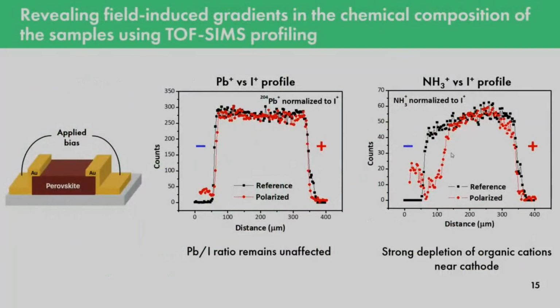TOF-SIMS analysis allowed us to understand better what's going on inside the device. So we can see that the ratio of lead towards iodine after the biasing stays almost the same. But at the same time, when we look at the ammonium ratio to iodine, a strong depletion of organic cations is observed, and it's exactly at the same point where we observed this kind of canyon on atomic force microscopy.